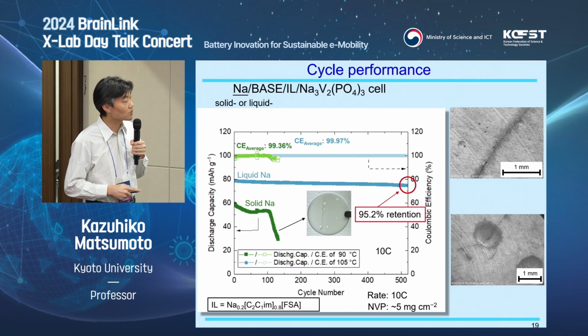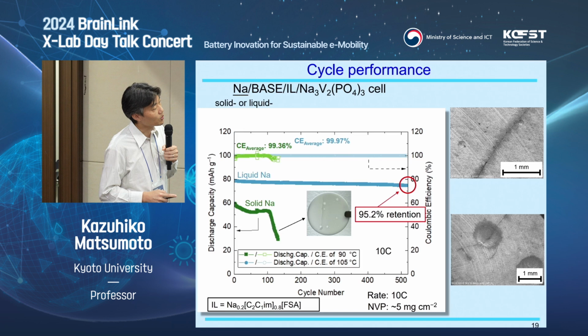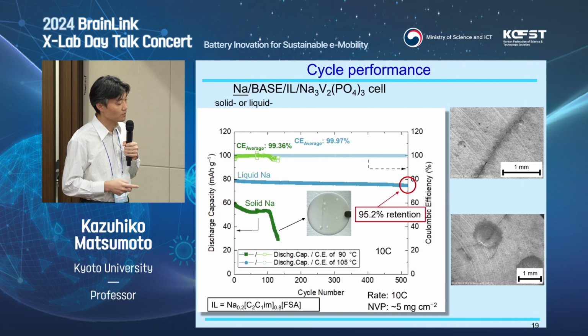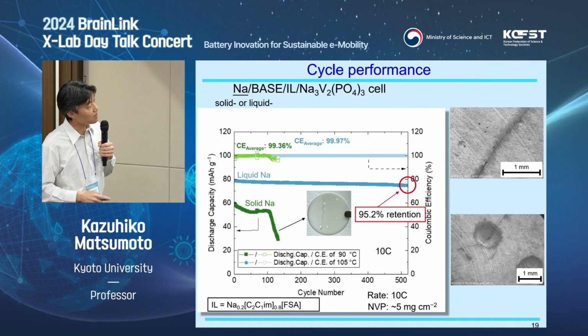So in the case of liquid sodium metal, it can go over 500 cycles, and we see 95.2% retention. It's very stable and without any problem. After this cycle test, we open the cell, but nothing happens. Well, in the case of solid sodium, the capacity decreases just in the 100 cycles and then drops after 100 cycles. And we saw that surface of that beta alumina after the cycling test.